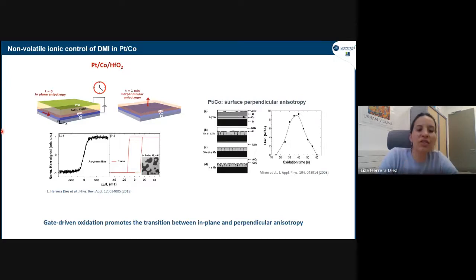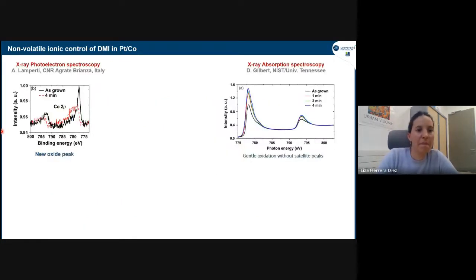This is really a gate-driven oxidation that promotes the transition between the in-plane and the perpendicular anisotropy. So here, this you have seen already. So we turned to our collaborators to get a little bit more characterization about the chemical characteristics of our magnetic film.